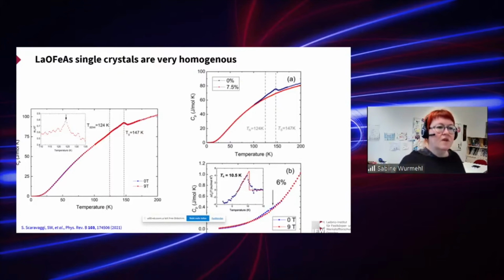And you can also do some cobalt doping in here. This is shown on the right-hand side, where you can suppress the spin density wave and structural transition, but at the same time, you can establish superconductivity, shown in the lower figure here. So this all demonstrates that we have very good sample quality.